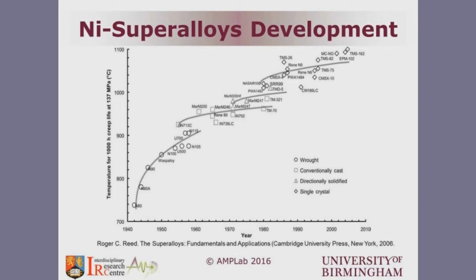From the 90s and beyond, we started to move into directionally solidified superalloys and then eventually into single crystals. Looking into how the temperature capability of nickel superalloys evolved within the last 60 years, you can see that we gained approximately 400 degrees in their temperature for creep life at 137 megapascal, as shown in that diagram.